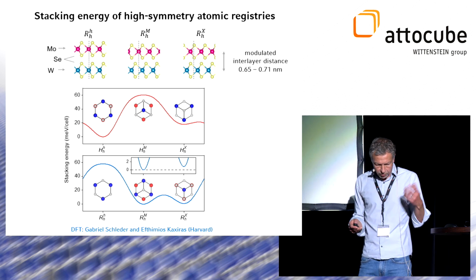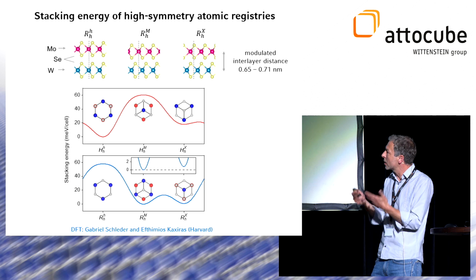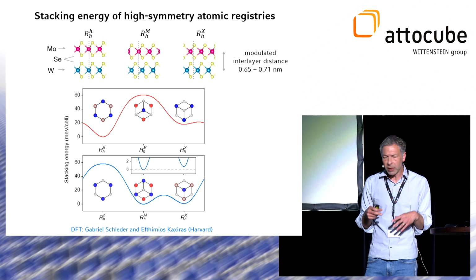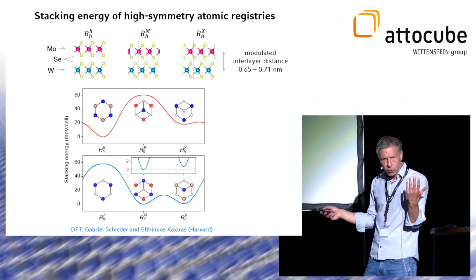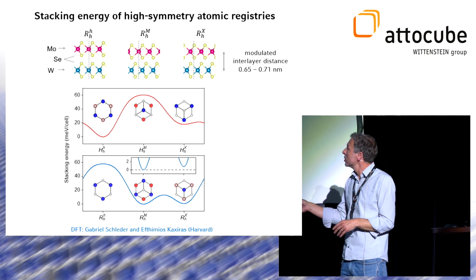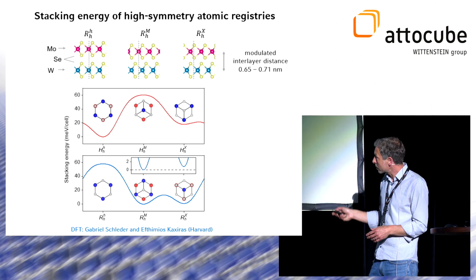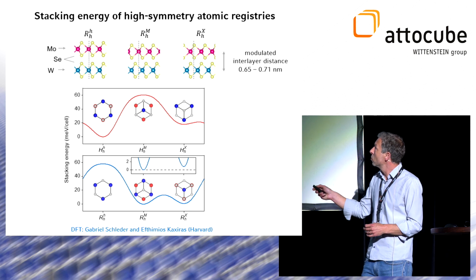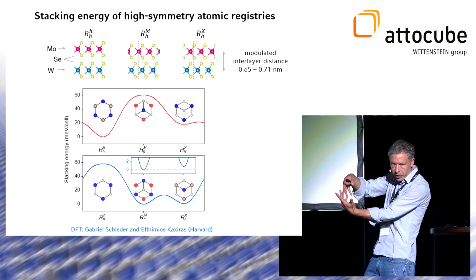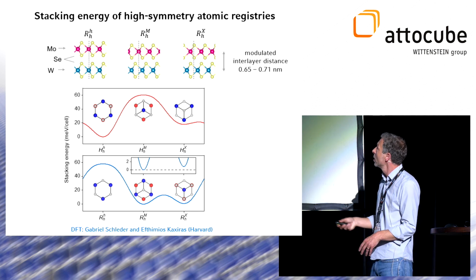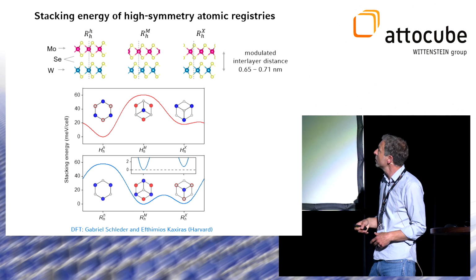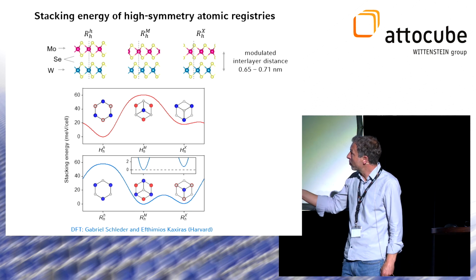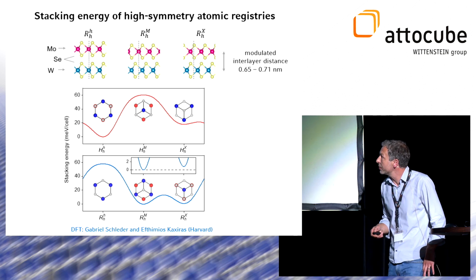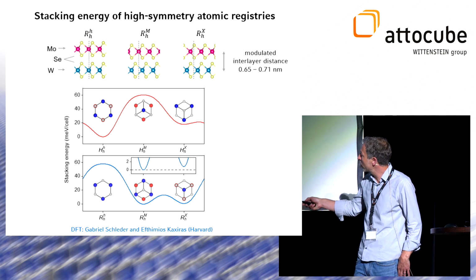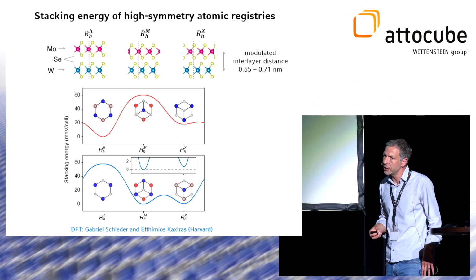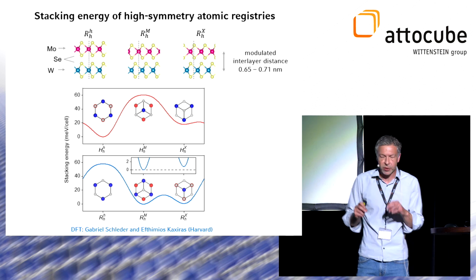If one calculates from first principles kind of the elastic or stacking energy that these registries realize locally, then it turns out that for the two configurations, parallel versus anti-parallel, there is a drastic difference in the penalty a wrong registry would pay, because the layers cannot interlock in the form of a zipper to minimize adhesion energy. So the atoms are simply in place, and there is a global energetic minimum for the HHH registry for anti-parallel samples, and there are two competing for survival, two registries that are close in their energy yet still somewhat distinct.